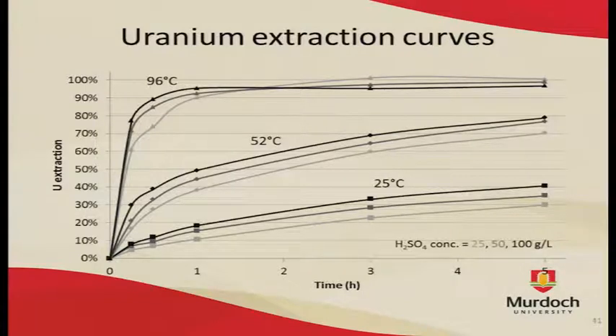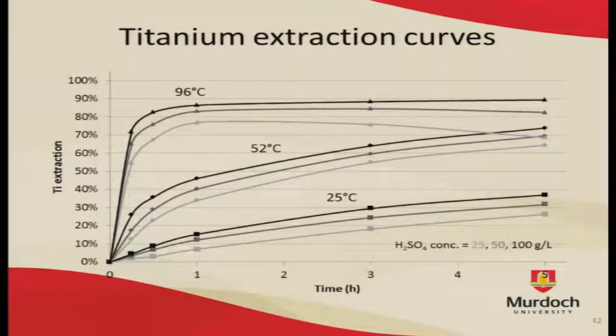Increasing the concentration of acid had a slight but consistent effect on the rate of uranium dissolution, and similar trends were observed with titanium extraction as well. Temperature had quite a large effect on the rate at which it dissolved. And the acidity also affected the rate of titanium dissolution, but a stronger effect in the amount that actually stayed